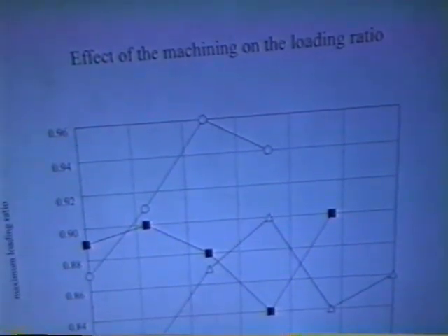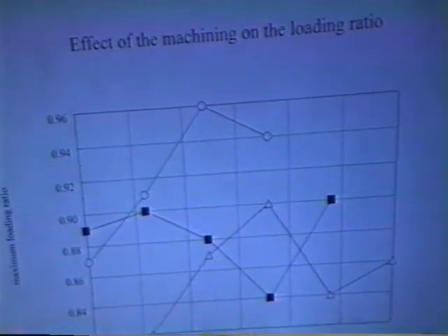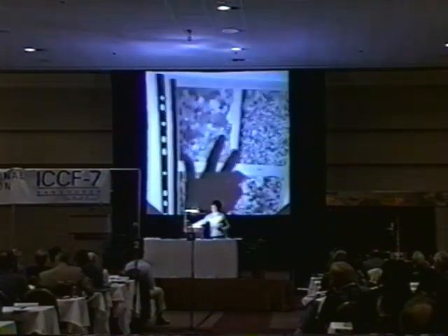What we found is this: there is a maximum in loading ratio versus the thermal treatment temperature. What does it mean? The thermal treatment has the effect just of increasing the grain size. It is well known from the literature. You can see here.